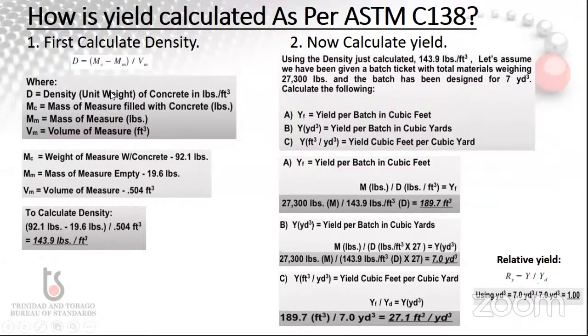So first, you need to calculate the density, which we would have already known the weight of the measure and the weight of the measure with the concrete divided by the volume, you get the density. If you have a batch ticket with the weight of, let's say, 27,300 pounds with a design volume of 7 cubic yards, simply divide the batch weight by the density you just got and multiply with this factor, and you get the actual volume of concrete in cubic yards. So relative yield is the ratio of the actual volume to the design volume. A value greater than 1 indicates an excess of concrete has been produced. A value less than 1 indicates the concrete batch is short.